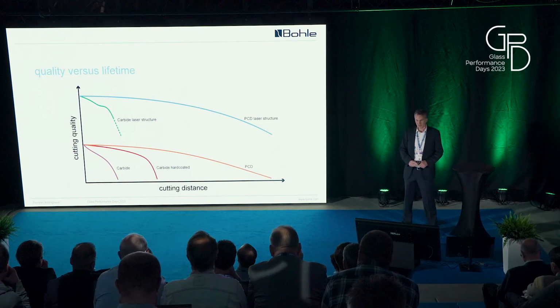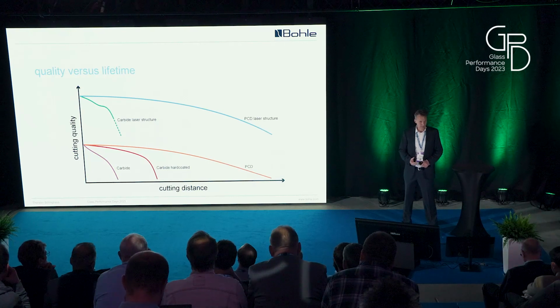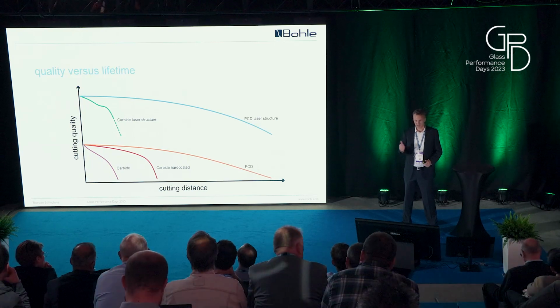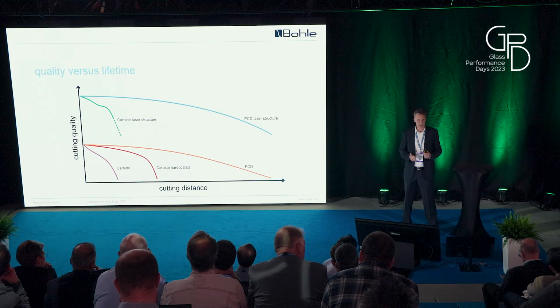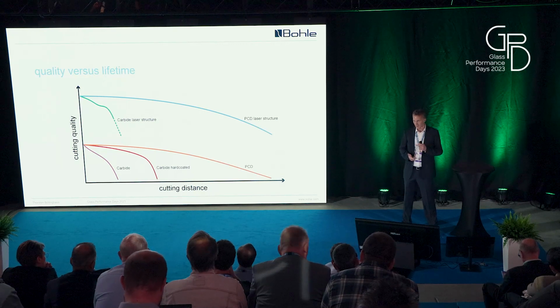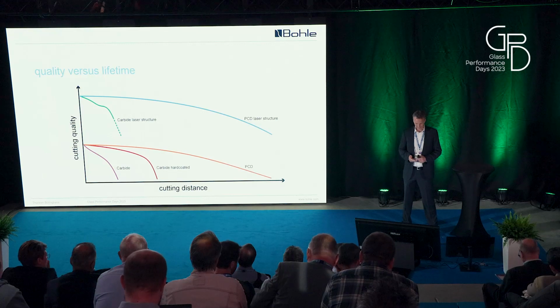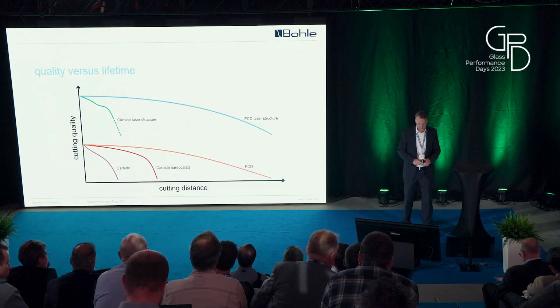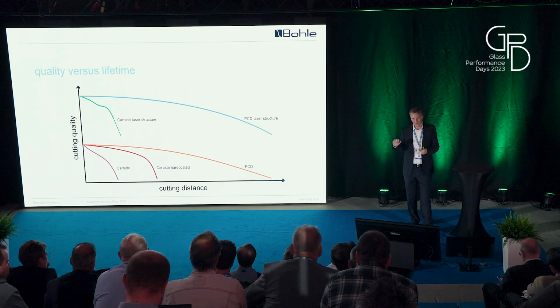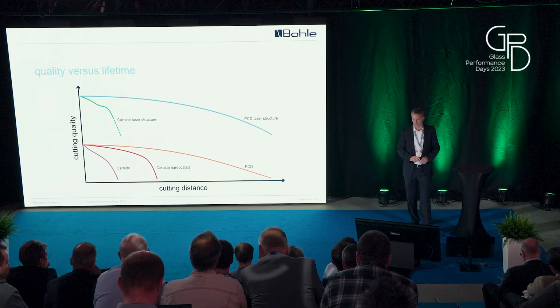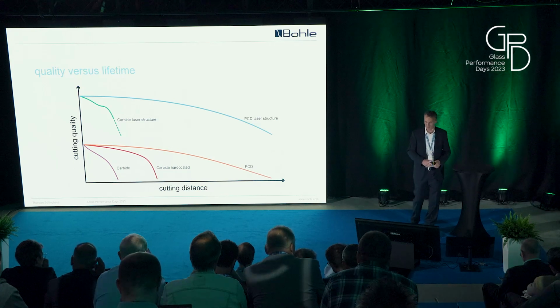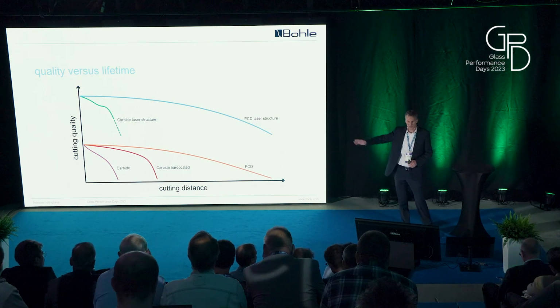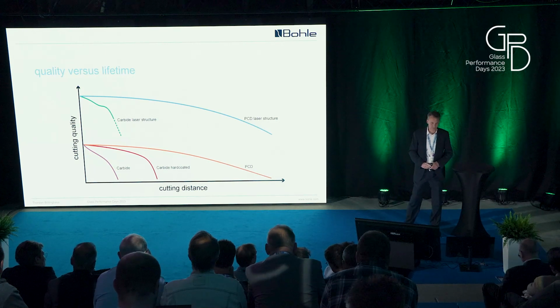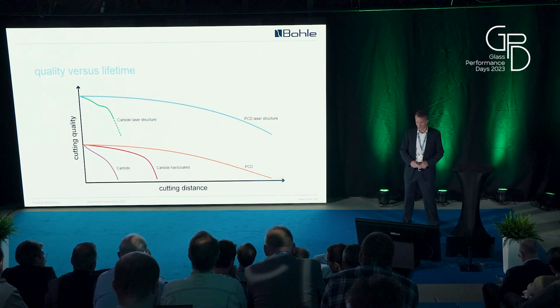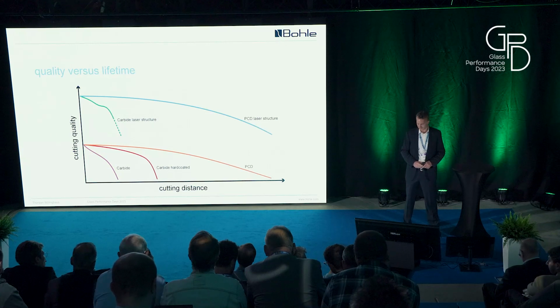And this can be very interesting also if you cut glasses which are very expensive, as we said. If you have a laminated glass that has been produced on the float line, cut, coated and then laminated, and you damage it, this is very expensive. And when do you normally change your cutting parameters? You change them once you discover problems, but you don't want to discover these problems very often. So you take a cutting wheel that creates very stable conditions for a very long time, and this can be a good application for this type of cutting wheel.